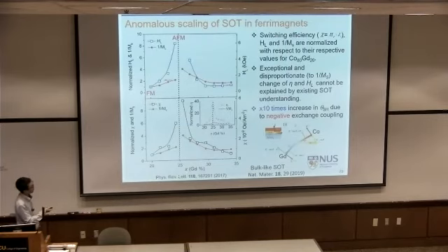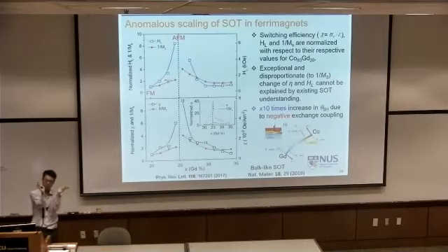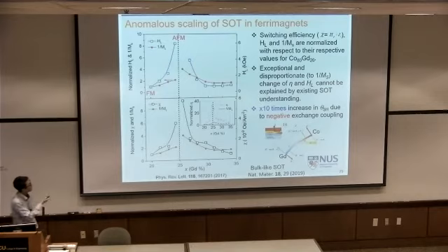And we found that about 25% gadolinium is close to antiparallel alignment, in which cobalt and gadolinium point in opposite directions. So your magnetic moments are closely compensating. And about 20% gadolinium is close to a ferromagnet, and the cobalt lattice dominates in this case.